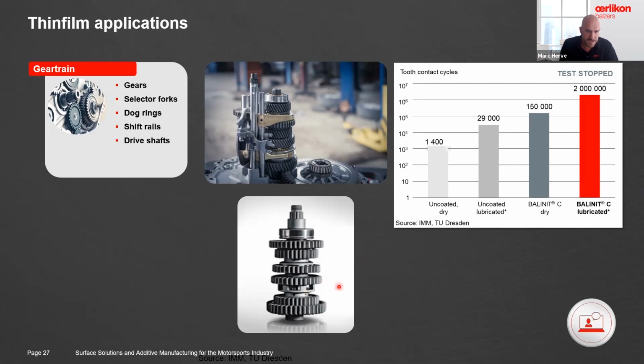So here in this case, we will remain with the carbon-based coating because we look to reduce the friction, but with a softer one. So this way, we create some kind of a running-in step that also does a little bit of transfer from one part to another one. And for the gearbox, the interest will be to have the coating and push back the pitting and the wear that you can see on some gears, for example, on the teeth. But then, we can coat also the shift drums, the selector fork, the dog rings. There is a lot of parts in movement inside a gearbox. And again, it's really case by case. And yes, harder is not always better.